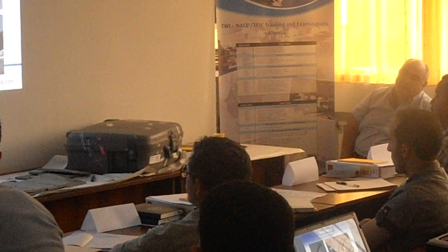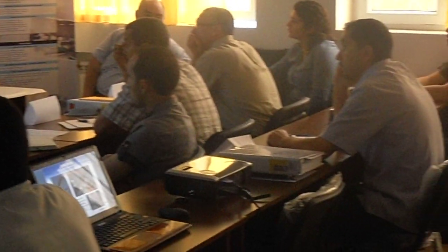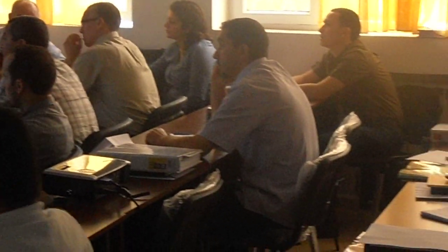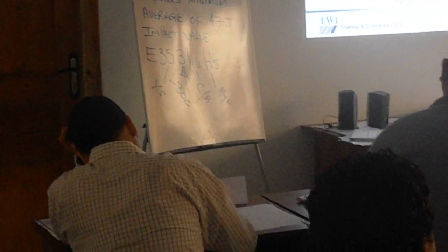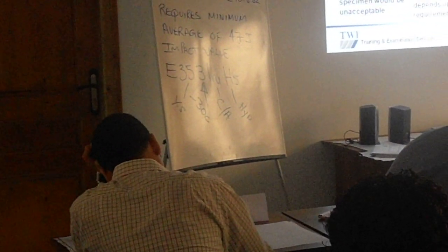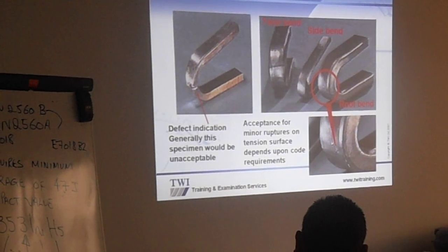I cannot say what's acceptable and what's rejectable because it's very dependent upon the code you are using. For example, when I first taught 1104, I could not believe you can have cracks. I had to read it about 3 times. I'm thinking my mind is playing tricks on me here. Yes, you can have a crater crack, as long as it's not more than 4 mm.